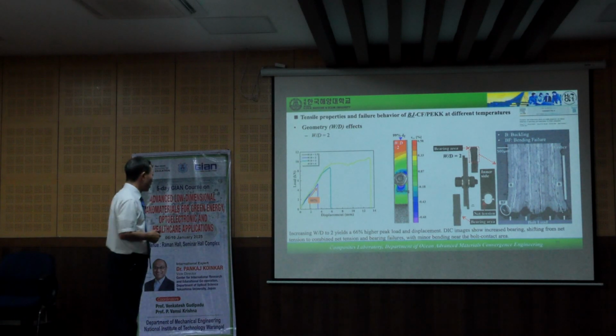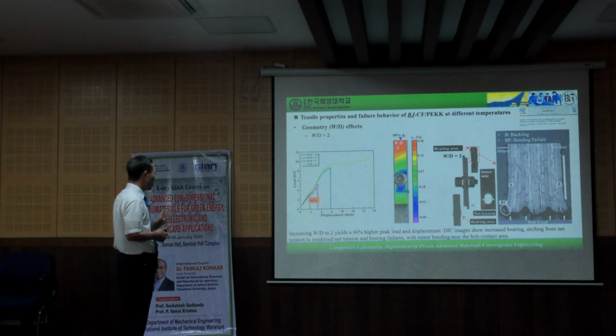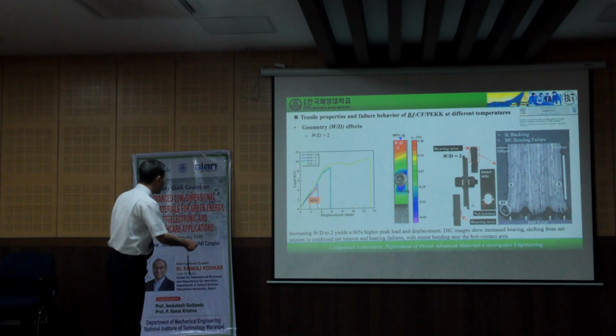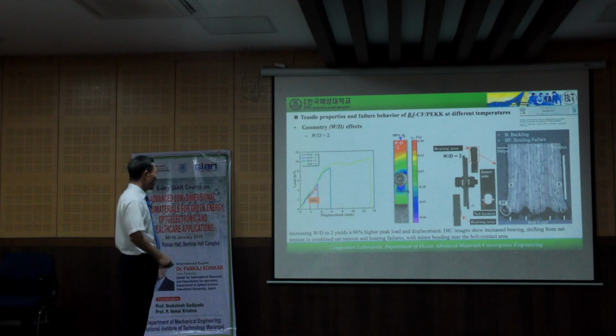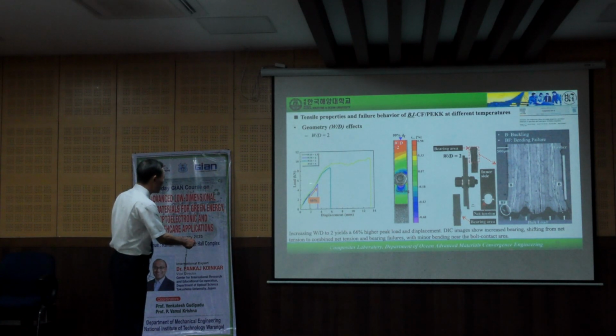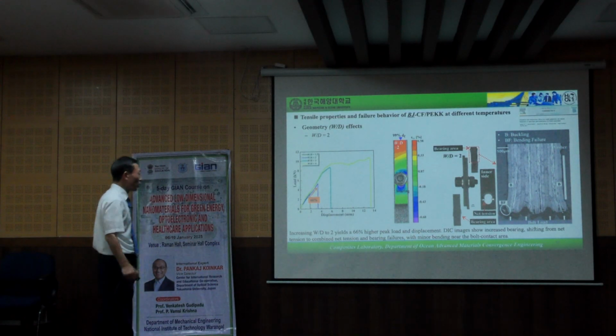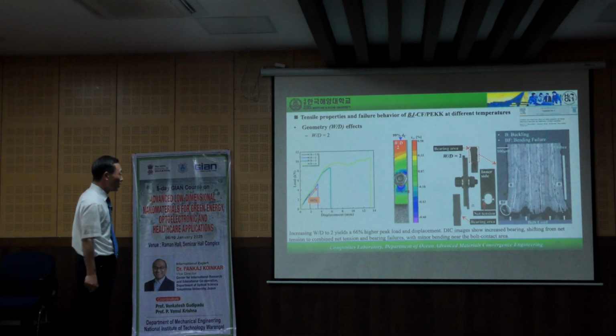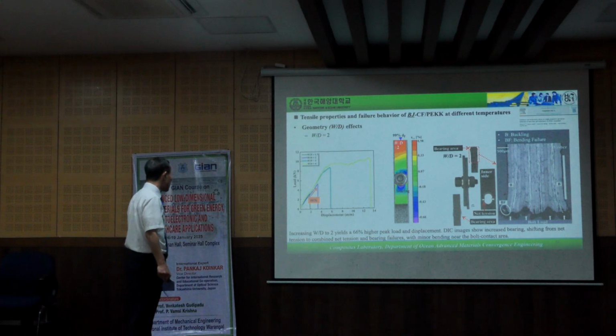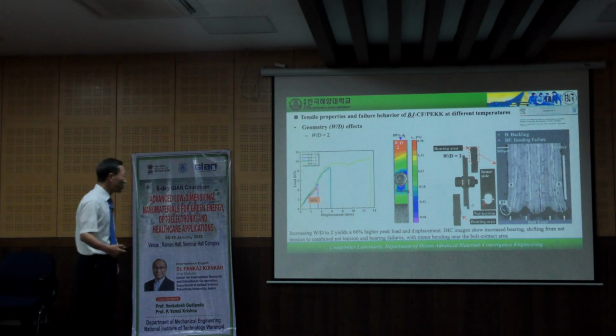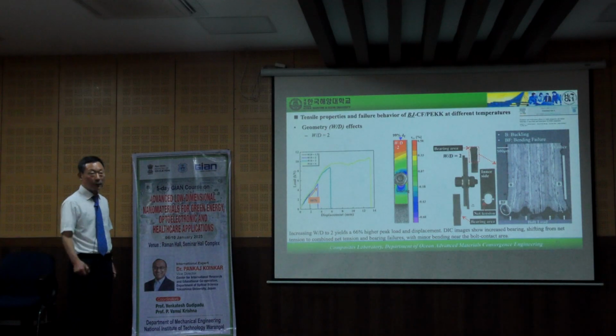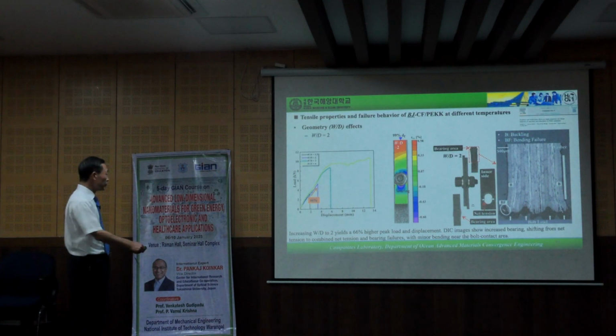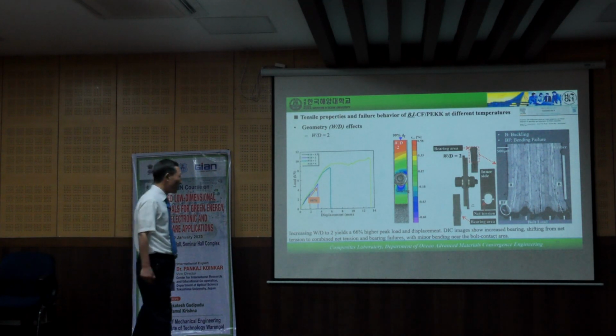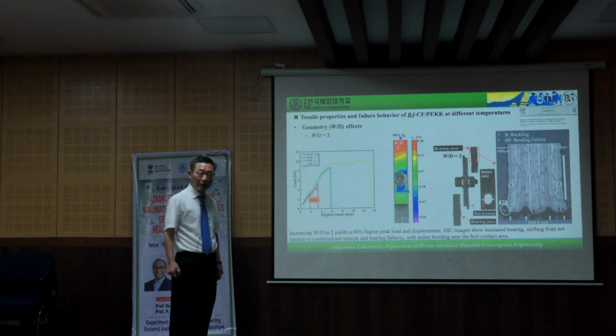Increasing W/D to 2 yields 66% higher peak load and displacement. DIC images show increased bearing, shifting from net tension to combined net tension or bearing mode, with minor bending near the bolt contact area.